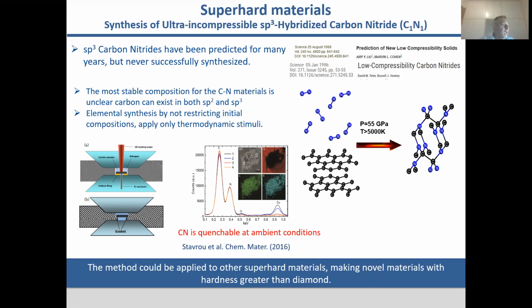In a lot of studies, the main problem was that precursors were used, which introduced the problem of impurities. In this case, why I like this study a lot is that we went through the hard way to use elements instead of precursors, graphite and nitrogen. So we mixed graphite and nitrogen in a diamond anvil cell and then laser heated at a given pressure, which created a lot of experimental problems. Laser heating the graphite, we all know what's happening if you don't do some tricks. And indeed, we managed to synthesize the carbon nitride. The surprise was that it was 1-to-1 instead of 3-to-4. And the pressure and temperature were, of course, very high. I don't claim that these things can have practical applications for these synthesis conditions, but I think it can pave the way for other compounds.